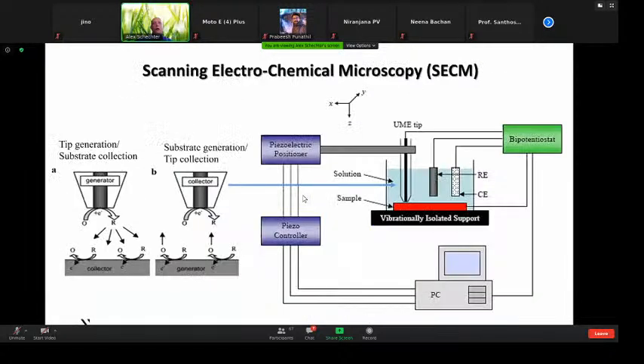That way we can embed into the tip, into the AFM tip, or to another microelectrode tip. We can embed an electrode, and then we'll have a sort of a shuttle reaction: oxidant going into reductant, and reductant goes to oxidant. We can do that reversibly, and so as we go closer to the surface, the current increases. That way, we can scan the surface, we can move it over the surface and measure the reaction that we're interested in as a function of position across the surface.